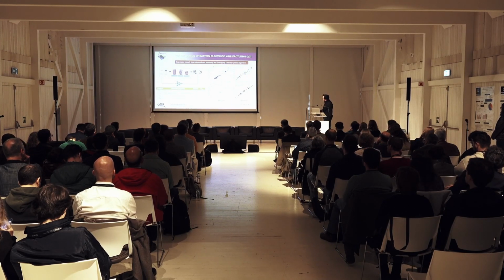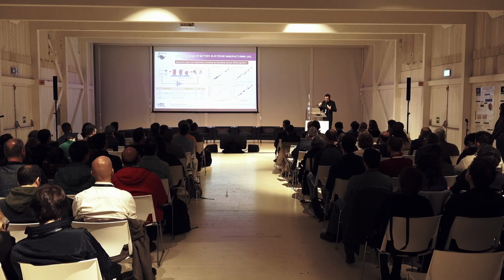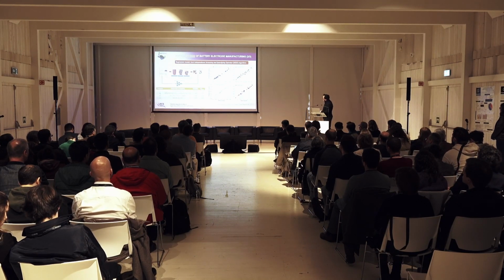our machine learning model. You see here the accuracy of this machine learning model at predicting properties such as the tortuosity factor of electrodes, the conductivity, the active surface area, the density. When this number, the actual score, is close to 1, it means that you have a highly accurate model. Once we are satisfied with the accuracy, then we embed it in the Bayesian optimizer. And then, thanks to this optimizer, we can predict the active material formulation, the solid content you need to have in the slurry, and the compression degree you